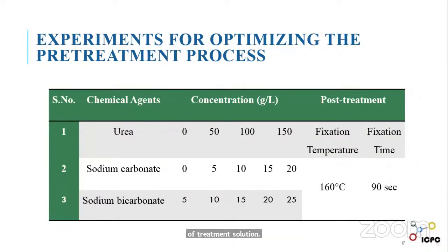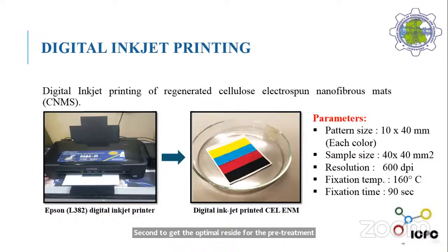But before digital printing, we optimize the concentration of chemical agents, such as urea, sodium carbonate, and sodium bicarbonate. We use different concentrations while fixing the post-treatment parameters, like fixation temperature around 160 degrees and fixation time of 90 seconds, to get the optimal recipe for the pre-treatment process. Further, we move to digital printing.